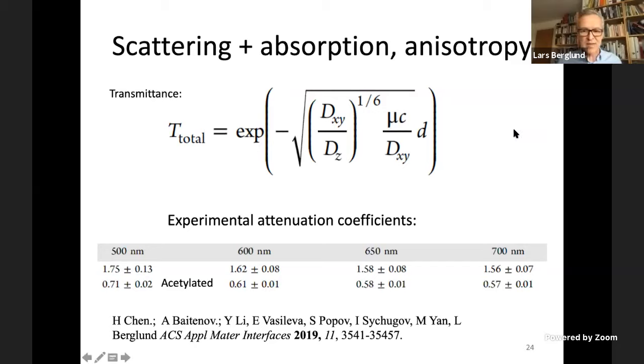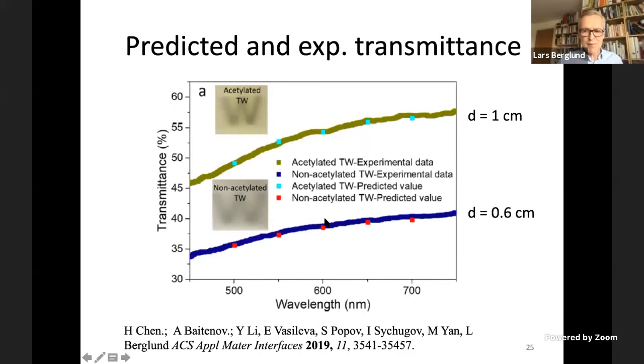And D is the thickness. But he basically lumped all these, with the exception of one attenuation coefficient that he determined experimentally, and used this simple expression for transmittance because he saw that it was exponential. And then he predicted data for another, much larger thickness. So in this case, it's 1 centimeter. And it turns out his prediction from data at much lower thicknesses is very accurate. And we can therefore use this to predict transmittance at other thicknesses.